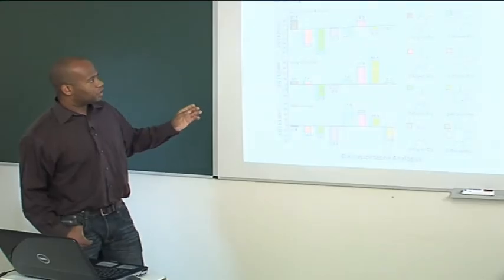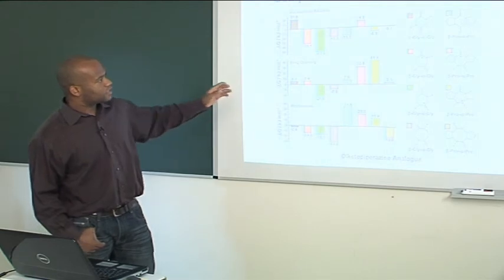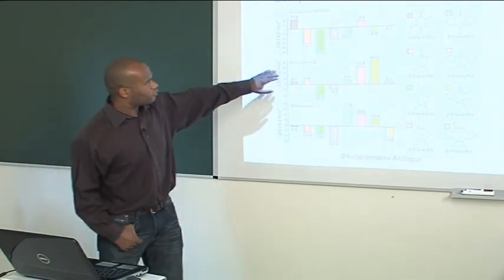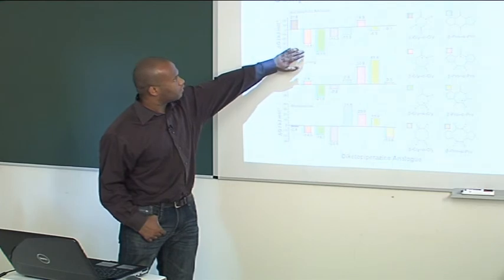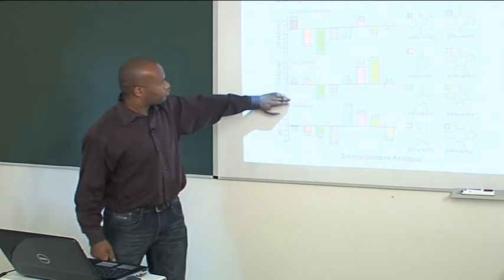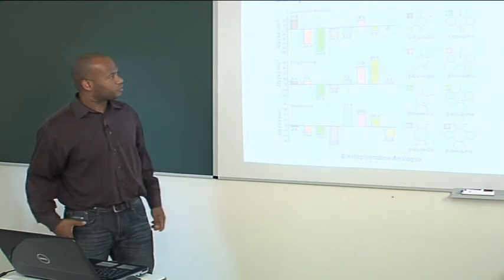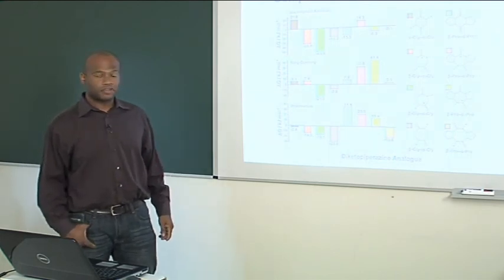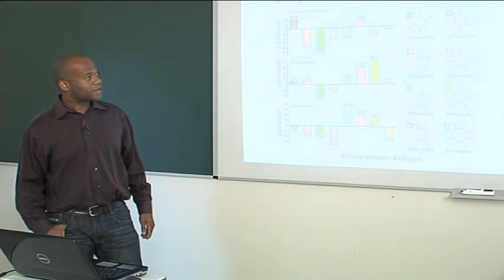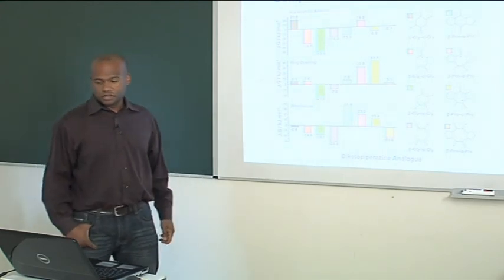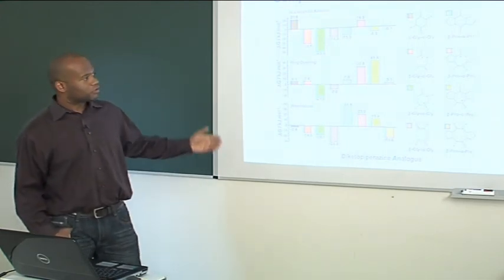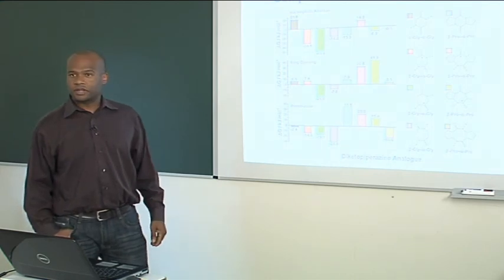But from combining the 3 reactions, we could see the 7-membered ring was most favorable with Gly because you had a negative value for the addition, for the ring opening, and the protonation. So from this data, we conclude that the 7-membered ring involving 2 glycyl amino acids is the most favorable. So then from this, we went and we already synthesized the 7-membered ring structures.